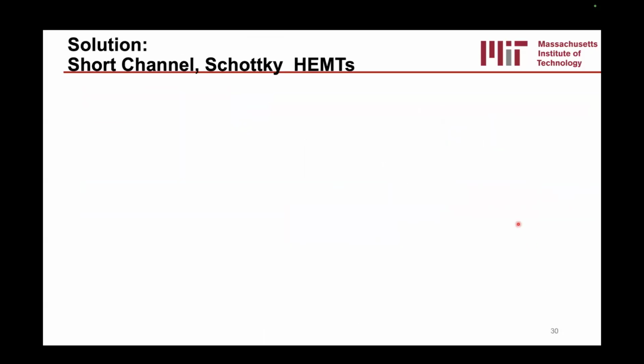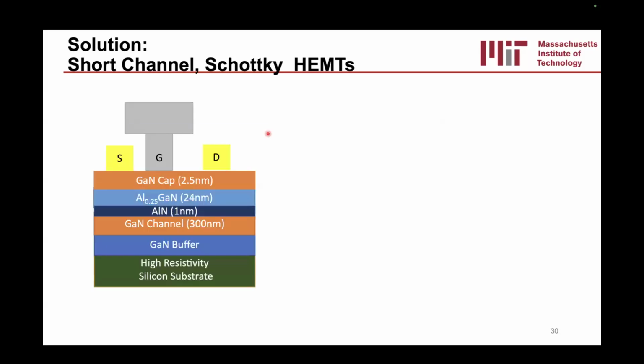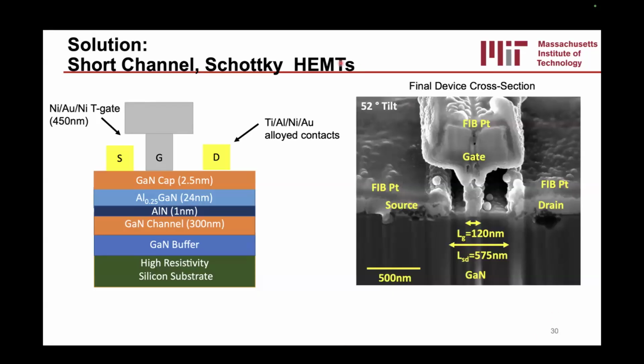All right, so the solution there is we don't want to be mobility limited. We want to make a very scaled device. So what we did is we started off with relatively standard Schottky HEMTs, where they use a nickel gold T gate, as well as Ti/Al/Ni/Au alloyed contacts. And this is a 24 nanometer barrier with 25% aluminum. And we made a very scaled version of that. In this case here, the gate length was 120 nanometers, and the source-drain spacing was 575 nanometers. And here's the source, drain, and gate right here.